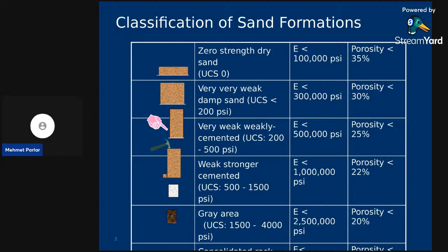This is a very rough classification of sand formations. Rock mechanics people in Schlumberger had put something like this together, and ever since we use it. Very unconsolidated, zero strength, dry sand is going to be basically unconfined compressive strength of 0. In other words, it already failed. It exists as individual grains. The second column is showing Young's modulus, and the third column is showing porosity. Young's modulus of these totally unconsolidated zones, if you like, is going to be less than 100,000 psi. Porosity is typically high, as high as 35%.